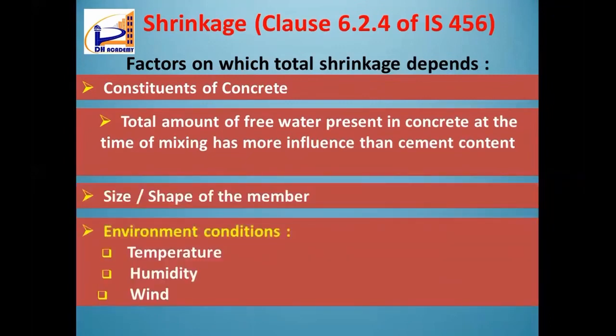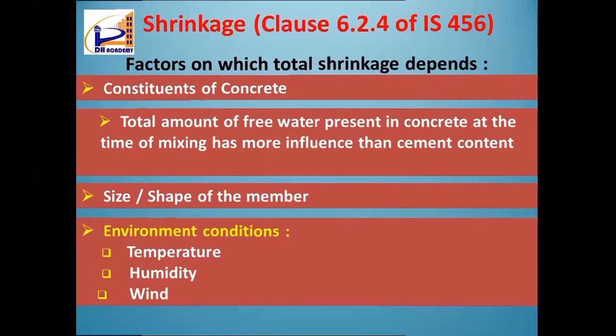There are three main villains for plastic shrinkage cracking, which is the most problematic in our Kerala especially, and other parts of India also, where the temperature is a little bit high in hot summer. So the environmental conditions, the main villains, are high ambient temperature, low humidity, and high wind velocity. These are the three environmental conditions which favor evaporation. And as per codes, if your evaporation rate is more than 1 kg per cubic meter per hour, we have to take all the precautions in doing concrete. Otherwise, the cracks may happen, right?